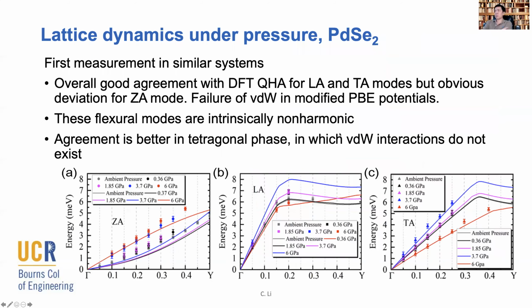So here are some pressure measurements we did on palladium selenide. I'm showing the results again plotted over DFT calculations. We performed the pressure measurement from ambient up to 6 GPa, across the phase transition. And here are a few things I want to show first. The first thing is that for the TA and LA modes, the agreement is actually pretty reasonable, as you can see in panel B and panel C.